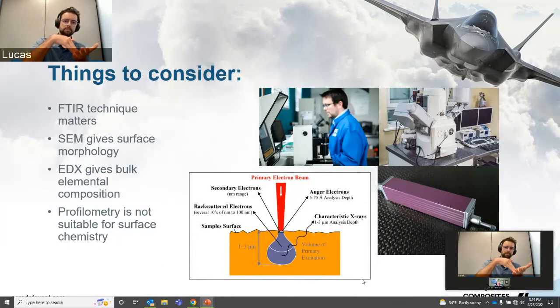ATR is sampling too deep. You can use grazing angle spectroscopy, but you need a reflective plate. It requires you to wash a part off in solvent, collect it on a reflective plate, and then you can get real thin film analysis on what's there. So it can be great, can be quick, not always the way to do it. Almost everyone's trying to do ATR, but it's not really even sampling the region that you care about. Another thing is SEM.